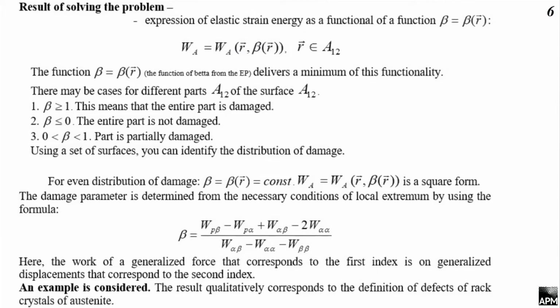There may be cases for different parts of the surface A12. If beta is more than 1, this means that the entire part is damaged. If beta is less than 0, the entire part is not damaged. When beta is between 0 and 1, the part is partially damaged. Using a set of surfaces, you can identify the distribution of damage.